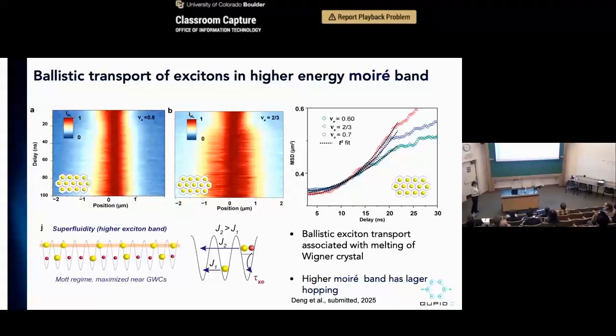You're still talking about the interlayer exciton? Yeah, this is still the interlayer exciton, but now I artificially push it up by the charges. When they co-occupy with a crystal, the exciton has to occupy higher states. And the reason why the crystal matters is that if the electrons are not crystallized, they just kind of flush around, and then the interaction between the exciton and charge will be less.